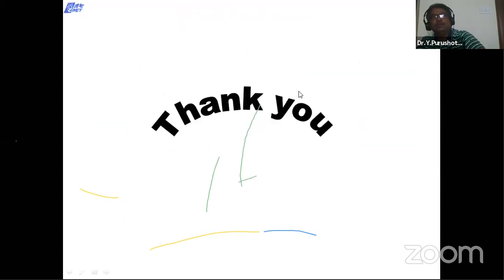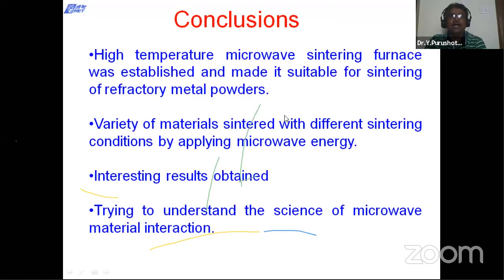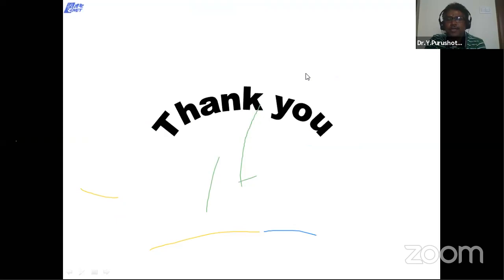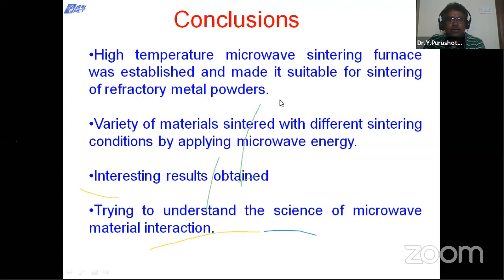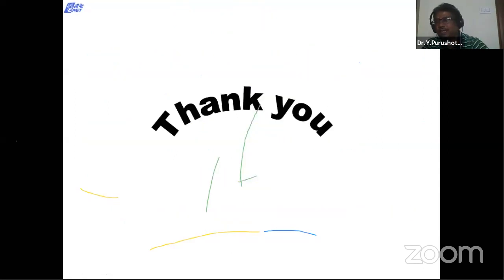So like this, now in the conclusions, a high temperature microwave sintering furnace was established at CMET, and we made it suitable for sintering refractory metal powders. A variety of materials were sintered with different sintering conditions by applying microwave energy, and we got interesting results. And with this, we are trying to understand the science of microwave material interaction. So thank you for your attention. This is the end of my lecture.